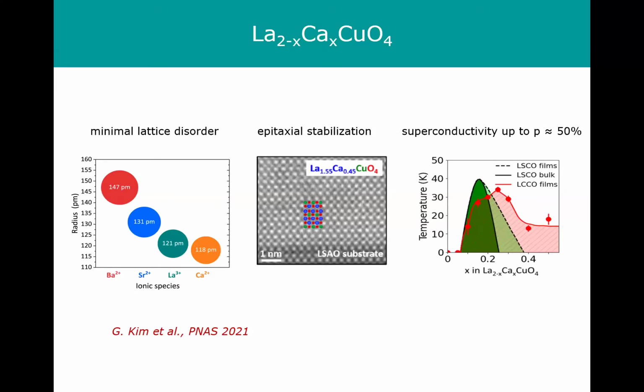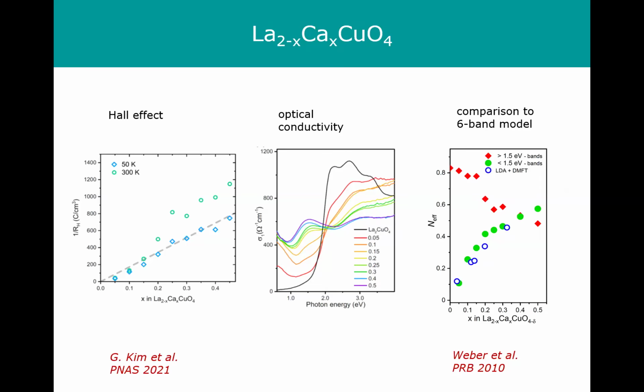Now, of course, it's pretty difficult to assess whether the material is really doped, whether the chemical substitution is really taking place. And we did the very best we could to make sure that this is indeed the case. For instance, we measured the Hall effect. It continuously evolves up to 50%. Optical conductivity also keeps evolving as you keep adding calcium. And some phenomenological analysis of the optical spectrum seems to be in pretty good agreement with what you expect in electronic structure theory, especially a six-band model proposed by Gabi Kotliar and collaborators.